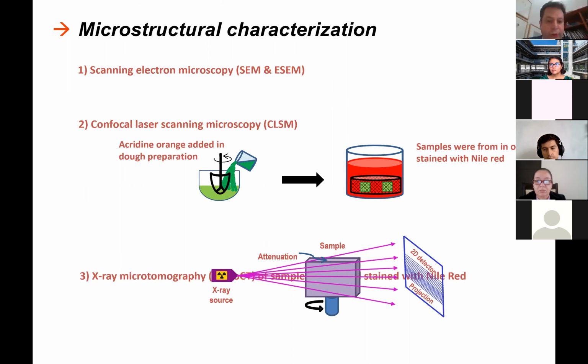So in order to avoid post-labeling during structure observation, what we have developed is that we have used fluorescent dye in the water that is being used to produce the dough, and we have fried them in an oil that already contains Nile red. These are fluorescent dyes that are needed in order to observe and characterize the structure using confocal microscopy. So we have developed methods that allow us to introduce the fluorophores that are needed in order to identify the structure during the preparation of the dough.